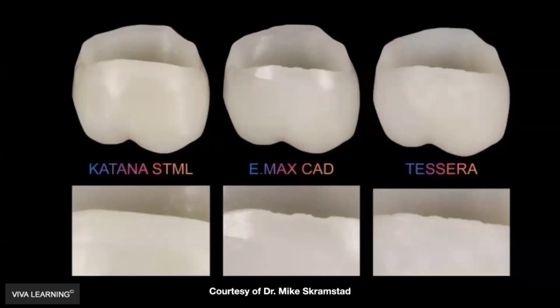So one of the main reasons that zirconia, especially Katana zirconia, is the workhorse in my practice is the milling. The mill mills this material at about 18 to 22% bigger than the actual final restoration. During the sintering process, the zirconia crown actually shrinks, and it becomes smaller by a percentage of 18 to 22. The mill knows this and essentially mills that material 18 to 22% bigger. That gives the ability to mill this in much finer detail with much finer burrs, and you get a much cleaner finish. And the material is also a chalky consistency, if you've ever seen any zirconia. And it can be milled in a much finer way. And you can see that just on the lower left with how clean that margin is.